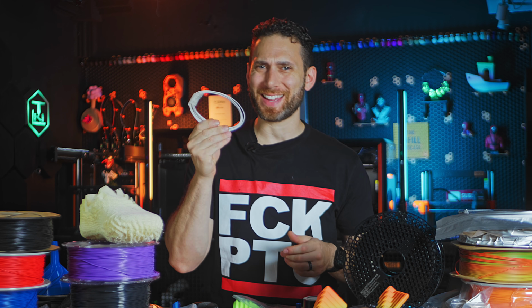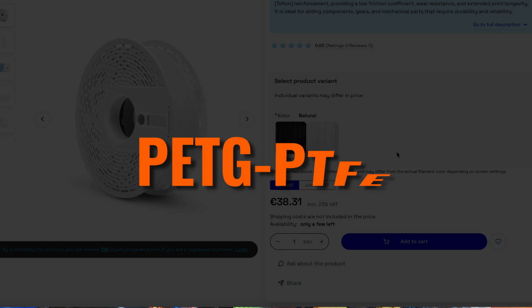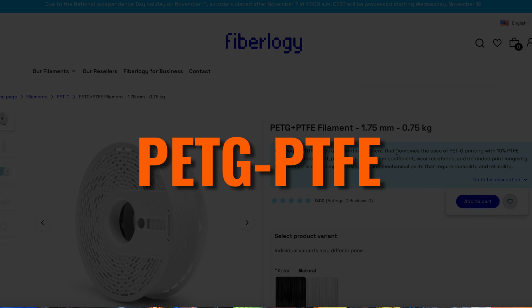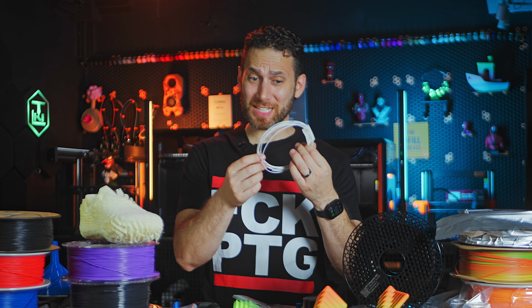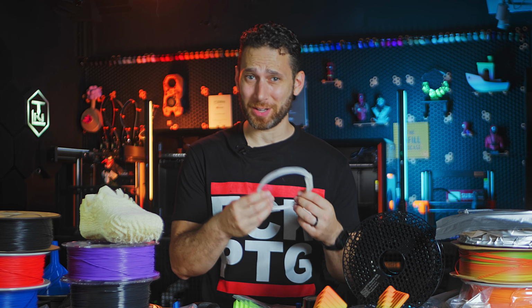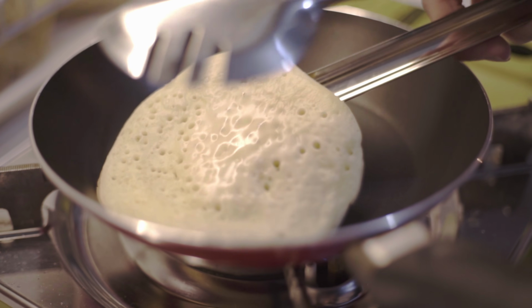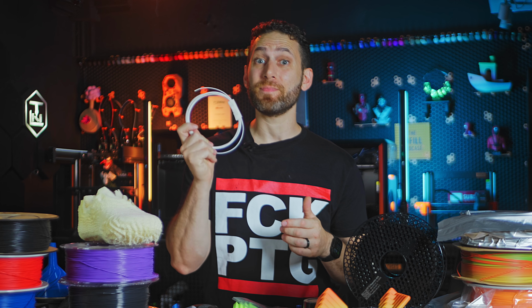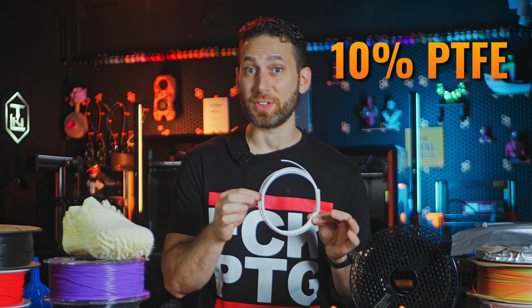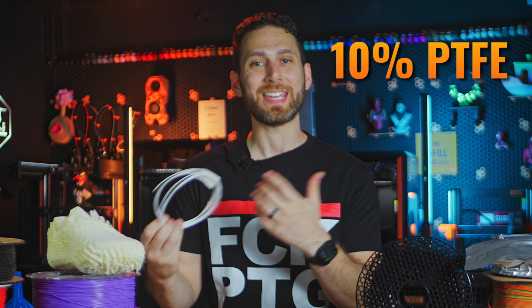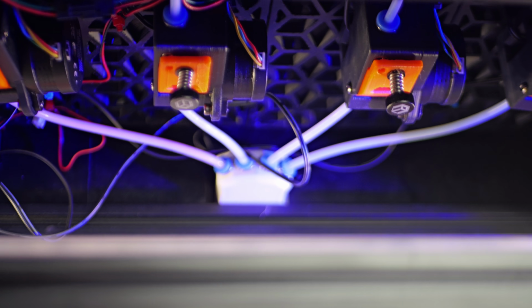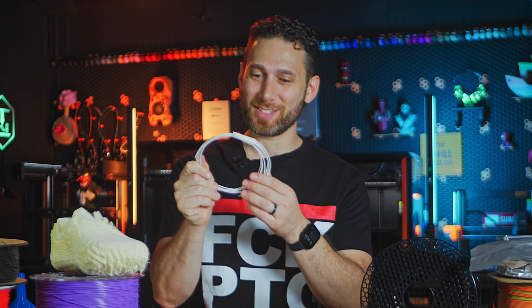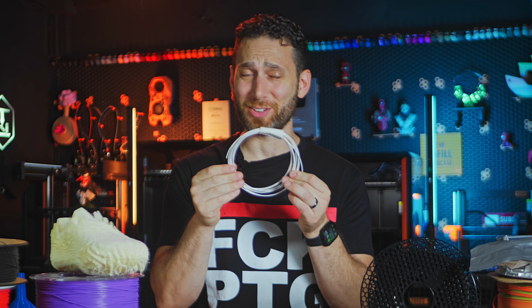If so, you just have got to check out this PETG-PTFE filament from Fiberlogy. Don't ask me how they did it, because PTFE, also known as Teflon, is notorious for not sticking to just about anything. But they managed to mix in 10% PTFE into this otherwise normal PETG. I actually used this filament to reduce the friction in the hub of my Box Turtle open source AMS when the filament kept getting stuck, and it worked a treat. I definitely need to get my hands on more of this stuff because it is very, very useful.